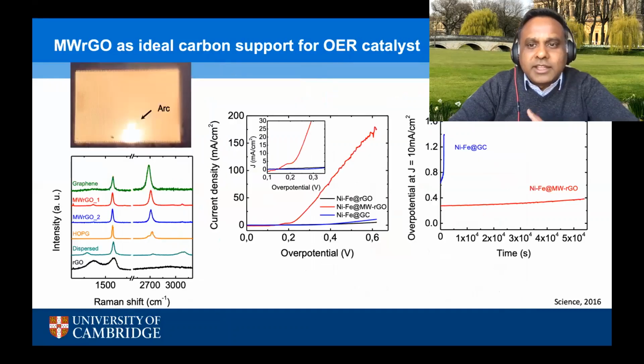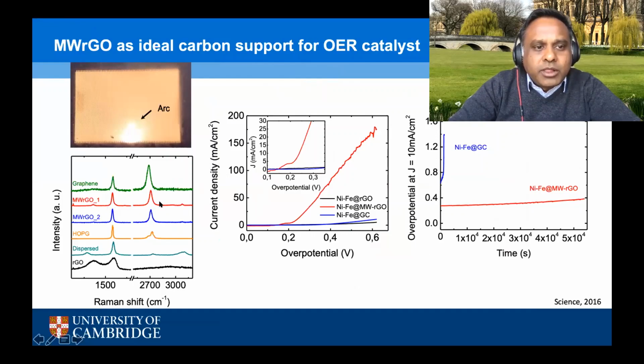So we've utilized that knowledge to design new types of supports for improving the catalytic performance. So this is results for the oxygen evolution reaction. So for splitting water to obtain hydrogen, one has to have the hydrogen evolution reaction and the oxygen evolution reaction. So both reactions have to occur simultaneously. So we've been looking at OER as well. And a few years ago, we showed that if one reduces graphene oxide by irradiating with microwaves, we can make this very high quality graphene-like carbon. And then if we put the catalyst on this very high quality graphene-like carbon that's GO reduced by microwaves, we're able to improve the performance of the catalyst with respect to if the catalyst was placed directly on glassy carbon or just on RGO.